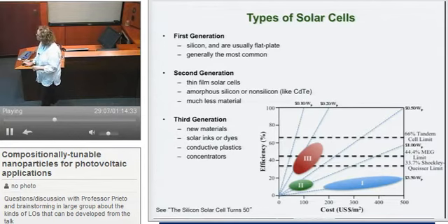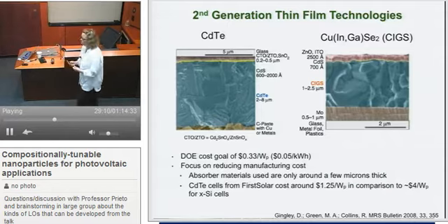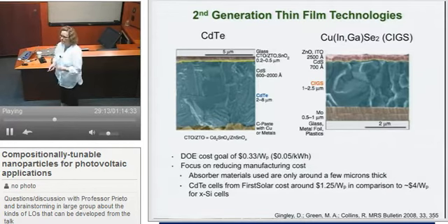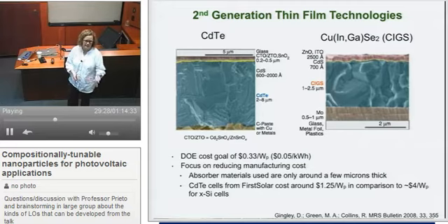Okay, so in terms of these second generation thin film technologies, the motivation in this field is that silicon cells require a lot of material on the order of 100 microns of silicon, and that's because silicon has an indirect band gap. So it's not very efficient at absorbing light, so you need a lot of it. Silicon is incredibly naturally abundant, but we get it from sand, which is SiO2, and sometimes I show the commercial pathway to go from raw quartz all the way to silicon, and there are lots of steps at very high temperature using very caustic chemicals. So that's why silicon, even though it's really abundant, is expensive. So people are looking at these second generation materials because they have direct band gaps, so you don't need as much material.